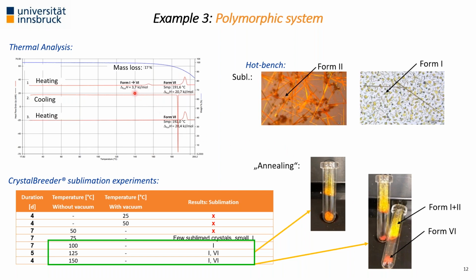Why is this? Because at higher temperatures, there I'm going back to a DSC curve, we start with form 1. We can induce the phase transformation, and if you keep the compound for a longer time, at, for example, this temperature range, we also already induce the phase transformation. And with this experiment, indirectly, we could check also the temperature. So here was the temperature gradient for the sublimation experiment. And I think this is a nice example that shows you also then via thermocycling or keeping your compound at certain temperatures, varying the sublimation temperature here on top of it, you can produce different polymorphic forms.